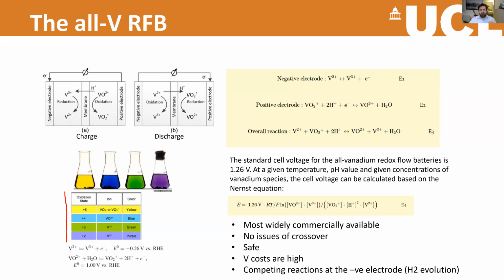When we use different materials in the negative and the positive electrode, then that's not possible. We have to do some sort of chemical separation to regenerate the capacity of the battery, and that's quite an issue. One of the issues with vanadium flow batteries is actually the negative electrode. This has a standard cell potential of -0.26 volts. And as I mentioned, that's all set relative to the hydrogen evolution reaction, which is set at 0. So that means if we're negative of that reaction, actually we have a competing reaction of generating hydrogen from water. And so the electrolytes that are used here are water-based. There'll be solutions of acid, of sulfuric acid probably. And so it's possible to generate hydrogen from these electrolytes.